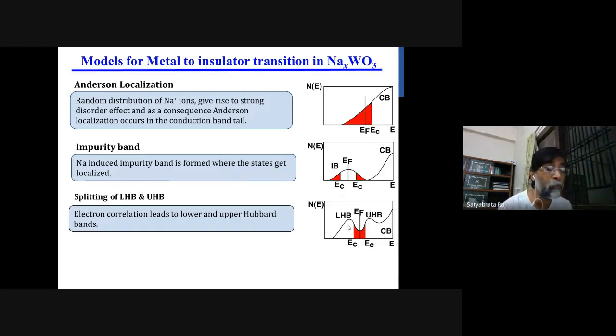What happens if you are putting sodium in the WO3, and this s electron is going to 5d, and 5d becomes a very strongly correlated electron system now. They repel each other, and the system becomes very correlated, and it can satisfy the Mott criterion, which is that the bandwidth can be equivalent to your Coulomb repulsion, and it will split the conduction band into sub bands, the lower Hubbard band and the upper Hubbard band. The lower Hubbard band can be fully occupied, and EF can lie in the gap, and you can have a metal to insulator transition. But for that, you need a very strong correlation that you can study later.